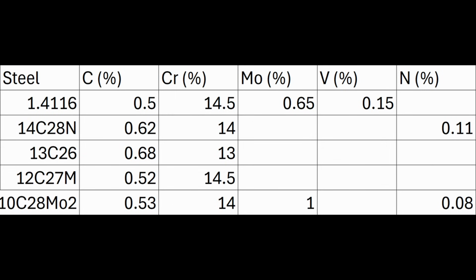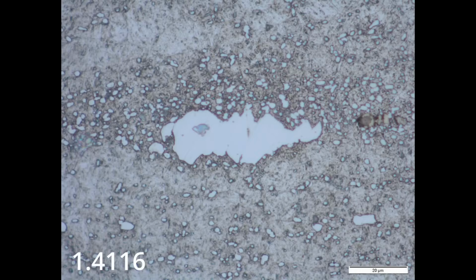Well, if you have too much carbon and chromium, you start to get chromium carbides that will form during solidification. And those carbides, when they form in the liquid, they don't go away. They are very large and they're very stable, and you can't get rid of them with further forging or processing. Now, forging and processing can decrease carbide size. So here is M7 high-speed steel. And when they start out in the ingot, those carbides that form in the liquid, they're very large, and as they forge the steel down, this happens before any knife maker ever sees the steel, the more reduction that it has, the smaller the carbides get. However, these carbides are still large, and they cannot be eliminated.